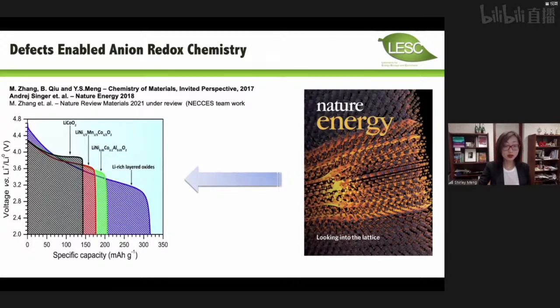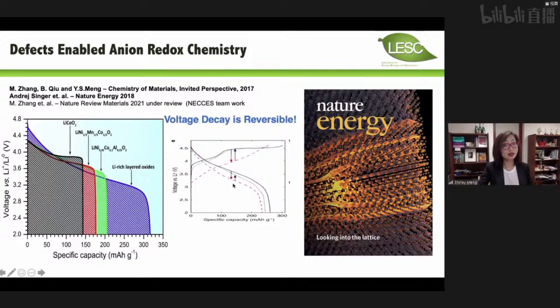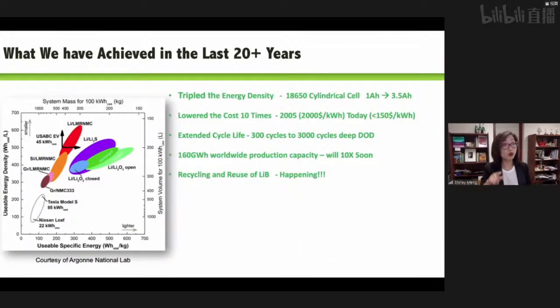I mean, it was widely criticized that this material has a voltage fading problem, but right now I think this voltage problem is completely under control because we now understand defects play a very important role in the voltage decay. By controlling the defect density, we can actually control the voltage decay, and we can predict the voltage decay.